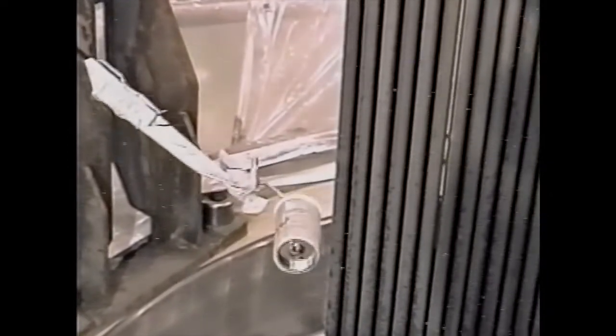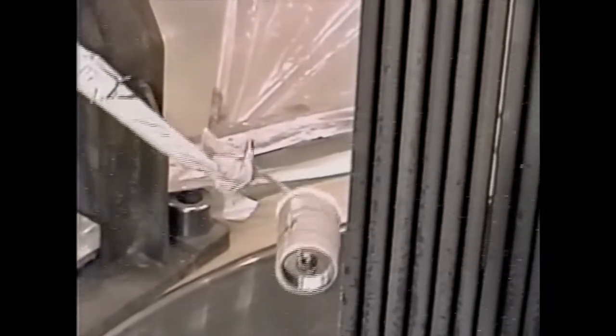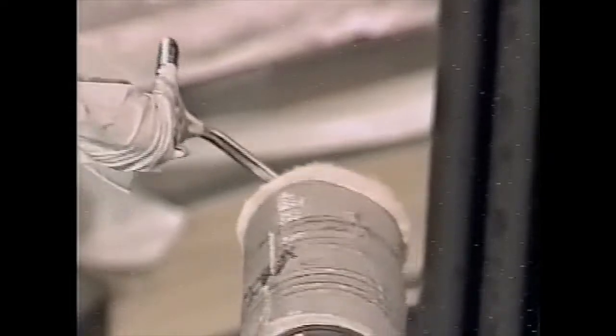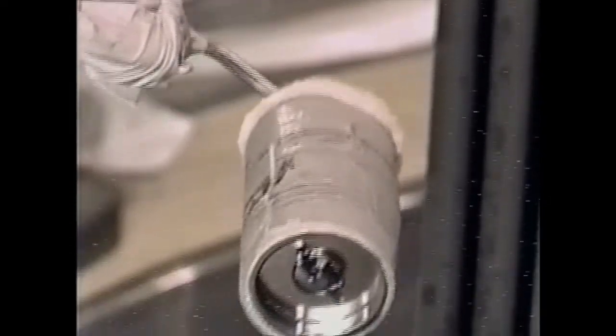Samples of crud and particles were retrieved for analysis using tape mounted to a roller or to a pad. The crud and oxide layers on the fuel assemblies proved to be highly adherent. Only small amounts of sample could be recovered, as seen by the material embedded in the fuel rod impressions on this roller tape.